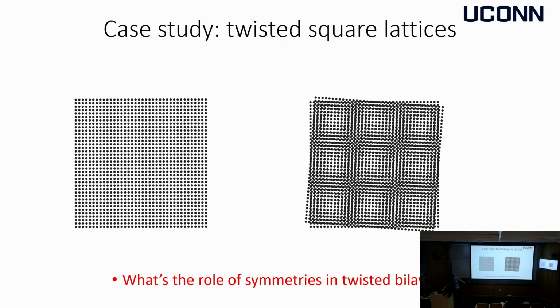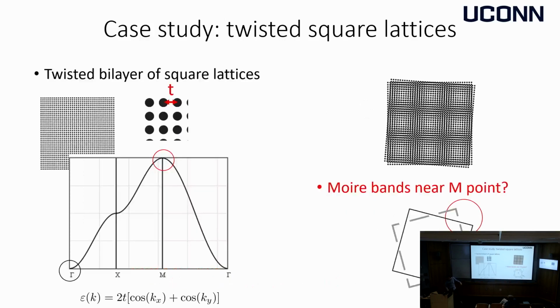So what we analyzed is what happens to the flat bands. So that's a single layer. That's the dispersion of electrons. Tight binding model on a square lattice. It has a minimum at zero momentum, has a maximum at the corner of the Brillouin zone. And then you look at these moire bands that form around this maximum.